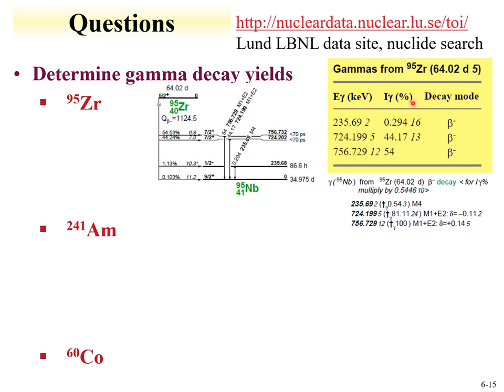So for zirconium-95, two photons are observed with pretty high intensities. One photon at 724 keV, one other photon at 756 keV. The 724 keV photon has an intensity of 44.17%, while the 756 keV photon has an intensity of 54%. So this means that 54% of the time for this energy photon, 44% of the time for this energy photon, those energy photons are emitted those percentages of time for every decay.